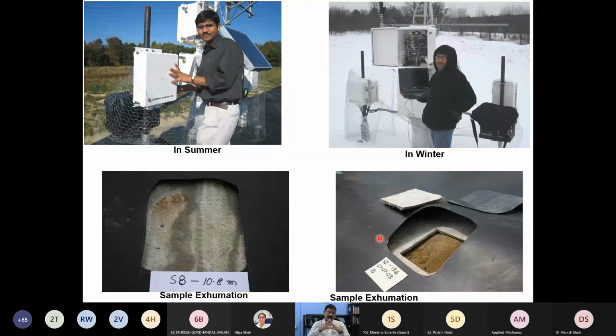So based on this, we have shown very clearly that the liner is going to perform very well in laboratory conditions in a very controlled fashion. We have also got some more inputs from the field data, and we said that this liner is really good, provided you use a proper liner material. Otherwise, it's going to be bad. Based on this work, you cannot really say that all geomembranes are going to last for 80 years. If the membrane is not made using a proper composition and proper chemical properties, eventually your membrane may rip within 5 years. There is no doubt. You don't expect anything more than that.